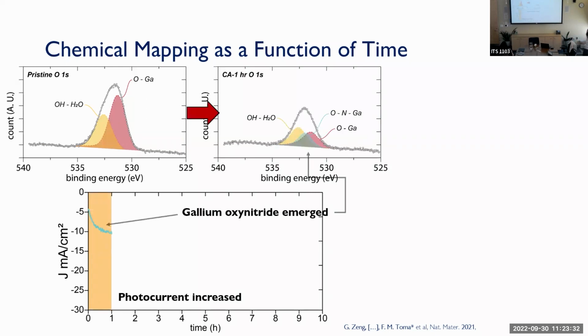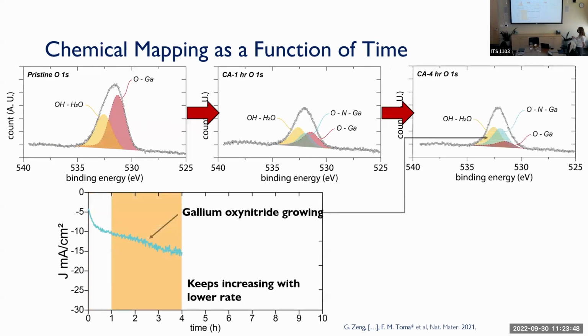Then we start running our measurement, and what you see is that there is a new peak. And in literature, we found that this new peak that was forming was probably related to oxygen bound to nitrogen of gallium. And this component kept increasing over time, and we reached a kind of a maximum at about 4 hours.